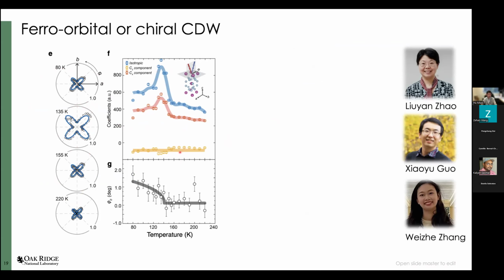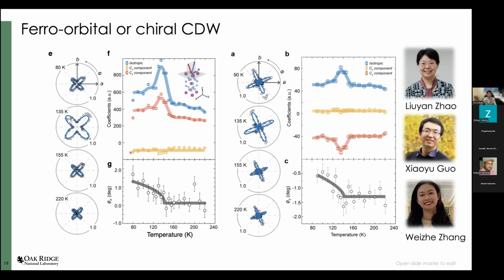What is really interesting is that below the CDW, the pattern rotated away from the high symmetry directions. What that means is that below the CDW, all in-plane mirrors are broken. And this is not only observed in one sample, we can confirm it in multiple different samples. That means below the CDW, there's no mirror symmetry in the system.